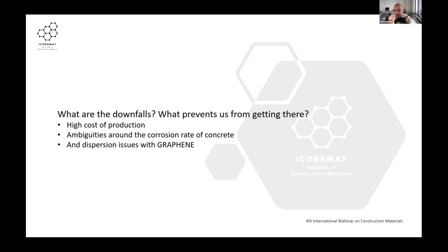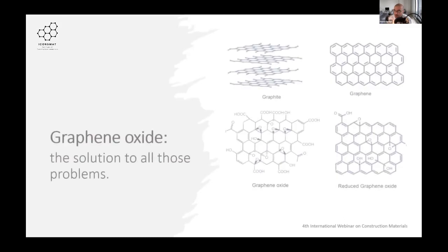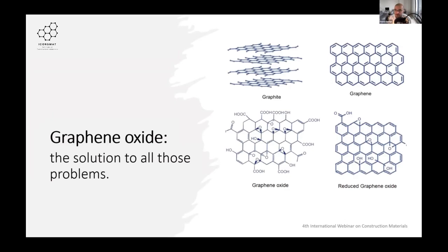Luckily, there is a much cheaper way of producing a material really similar to graphene that is called graphene oxide. Graphene oxide shares a lot of similarities with graphene, such as high compressive strength and both high electrical and thermal conductivity. In contrast, however, it is not hydrophobic, and I mean graphene oxide. Rather, it is hydrophilic, actually, because of the oxygen atoms, which means that it not only doesn't create chunks of little black balls, it actually helps in a better dispersion. That continuous path for electrical and thermal conductivity can be achieved by using graphene oxide instead of graphene in concrete.